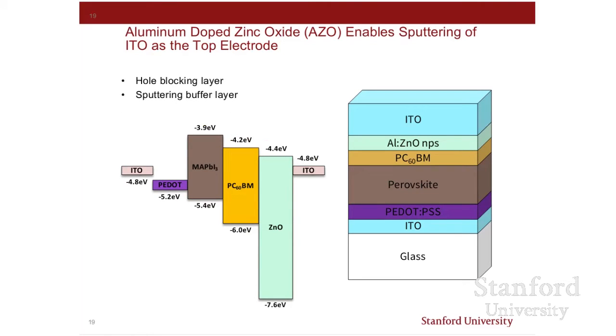My group has figured out how to mitigate some of these problems. We wanted to put a transparent indium tin oxide electrode on top. That's the material that's used in your flat panel display in your laptop. We wanted to sputter it, but it turned out that process would damage the perovskite, so we needed to put down a buffer layer. And for that, we used aluminum-doped zinc oxide nanoparticles. We could deposit those from solution in a way that did not damage the perovskite. And then we could sputter on that. These are inorganic nanoparticles. They're a little more robust, and they would protect the perovskite.